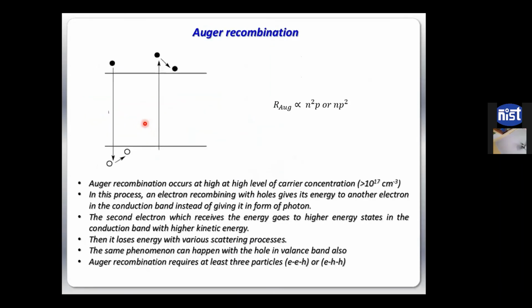And similarly, the other recombination, Auger, will depend, as I said, on at least one collision being required, right? So that means this kind of transition requires at least three particles, either a hole, electron, electron, or electron, hole, hole, right? So how many such electrons there are, in n square p, or how many holes there are, will control the rate. The more populated the conduction band and valence band are, the higher the probability of Auger recombination. Usually it has been seen that carrier concentrations of more than 10 to the power 17 per centimeter cube are required when these Auger recombinations start taking place, right?